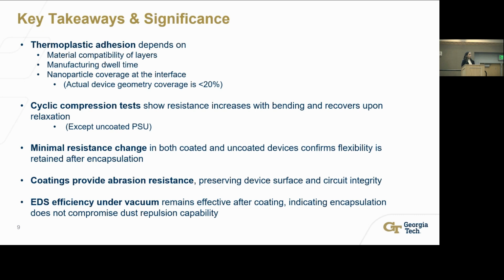So now I will be wrapping up my presentation by giving you some key takeaways and summarizing what we found with the significance. So what we have seen is that thermoplastic adhesion depends on various factors such as the material compatibility between the layers, manufacturing dwell times, and the nanoparticle coverage at the interface. And with the cyclic bending test, we've seen there were no drastic changes to the relative changes in the sheet resistance, neither with coated or uncoated devices, which is confirming their flexibility for dynamic applications. And we've also seen that although the resistances might increase with bending, they recover upon relaxation. So it's reversible electromechanical behavior.